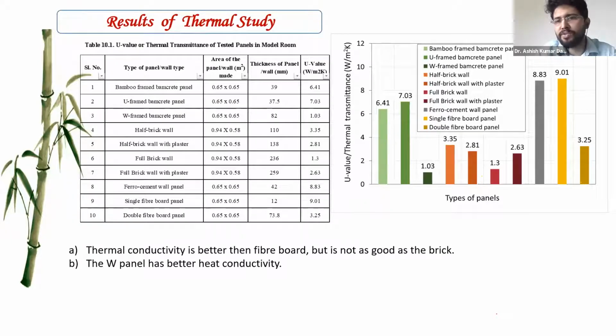And the concrete walling system is quite comparable with others, and it is in the range of the fly ash bricks, which is presently used. No doubt the burnt clay bricks have a very low U value. But the twin leaf system of the concrete walling system has very good thermal insulating properties because of the gap that exists between the two meshing systems.